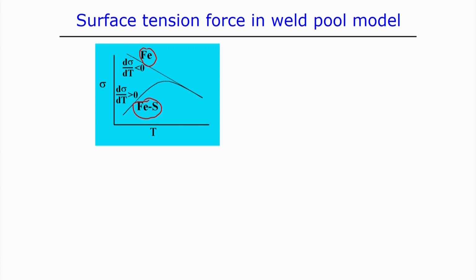So, in this case with respect to temperature, it has a positive slope up to a certain point, reaching the optimum value, then the slope becomes 0, and with further increment of the temperature the slope changes to negative. Up to that point it behaves completely differently from the pure iron system, but when you cross the optimum point the slope becomes negative, which is a similar situation to pure iron. So, there is no effect of the surface active elements beyond a certain optimum temperature.